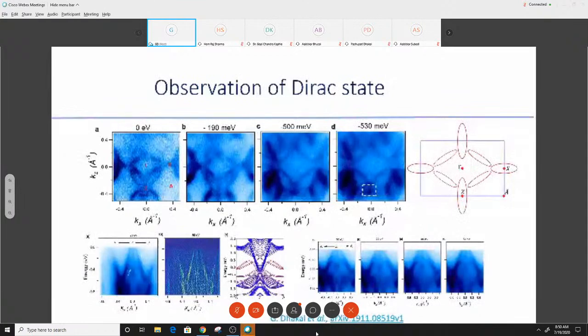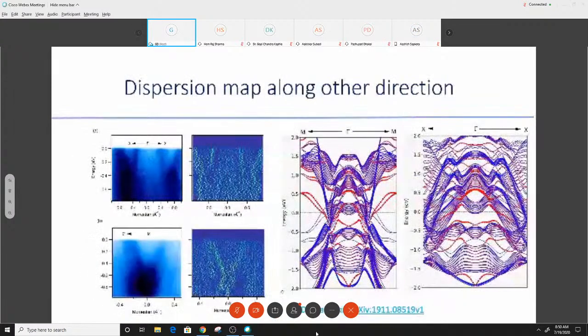And if you see the right side and the bottom side, it shows that the dispersion maps are taken at different photon energies, and the alpha band doesn't change with the photon energy. That indicates the surface nature of the band. Now we look at other directions, along Gamma-X and Gamma-M, and in these directions we also can see some linear band crossing, but they are not topologically significant. That is why the spectra we see is not strong enough.